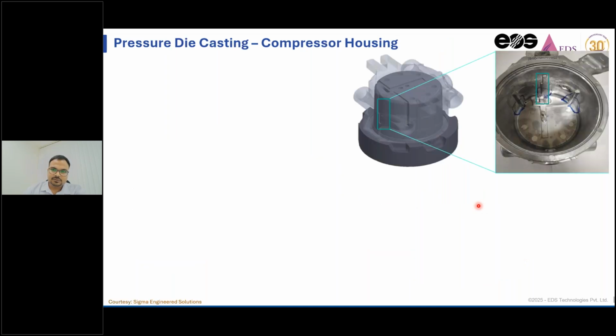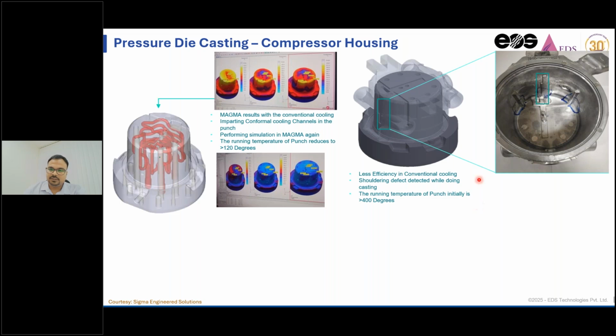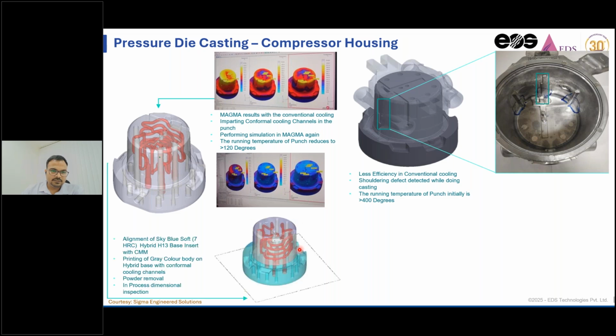In pressure die casting also, this is one example I have taken where the casting was having a great shouldering effect inside. That was a real defect during the casting process. So simulations were saying that the cooling was not efficient, and we tried introducing the conformal cooling on it, and then only this complicated portion was printed. So this is also possible. This we call hybrid printing.